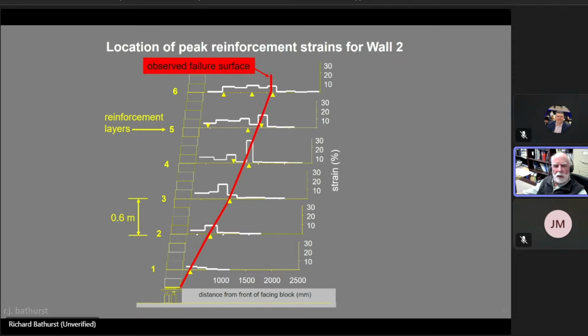And what you can see is that this observed failure surface is in reasonable proximity to the peak strains that we observed in the wall. The failure surface is non-linear and perhaps best described by a log spiral surface, and is shallower than the predicted Coulomb or Rankine failure plane that we assume in some of these earlier design methods.